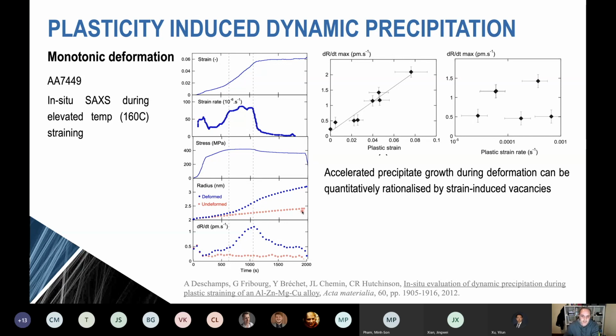during the plasticity. And as it turns out, quantitatively, we can understand that acceleration in terms of the effect of strain-induced vacancies. And of course, there's many different modes of coupling between plasticity and precipitation, and they all have different signatures in terms of their strain rate, etc. dependence. In this case, we're able to rationalise it pretty well using strain-induced vacancies. Now, this is in monotonic deformation, and it's at elevated temperatures as well, actually. And monotonic deformation is interesting, but of course we can only apply it so much.